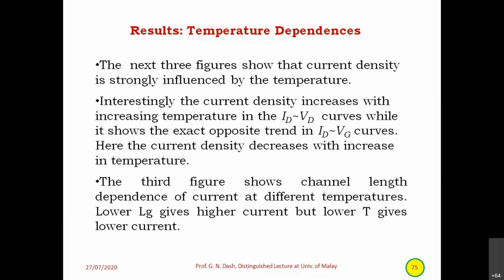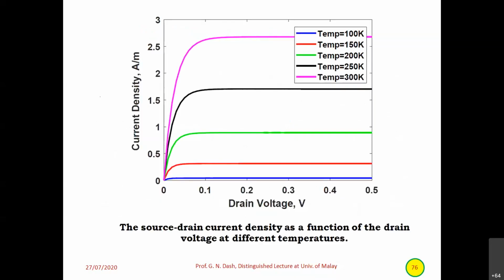The next three figures show that current density is strongly influenced by the temperature. Interestingly, the current density increases with increasing temperature in the ID versus VD curves, while it shows the opposite trend in the ID versus VG curves. Here the current density decreases with increasing temperature. The third figure shows channel length dependence of current at different temperatures. Lower Lg gives higher current but lower T gives lower current.